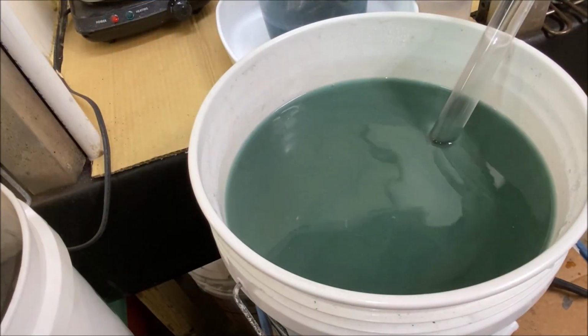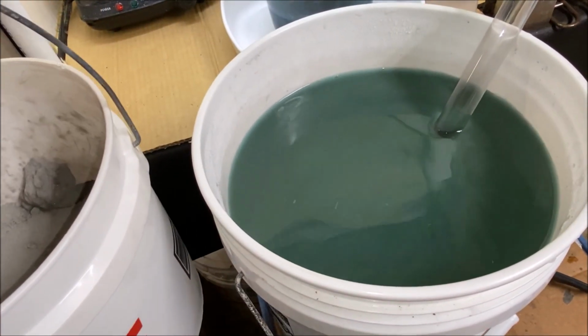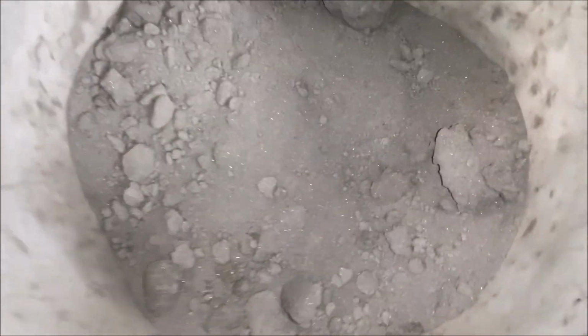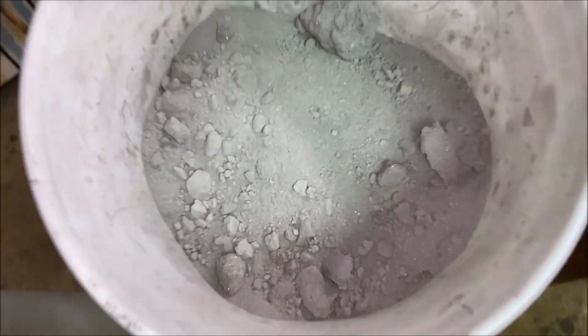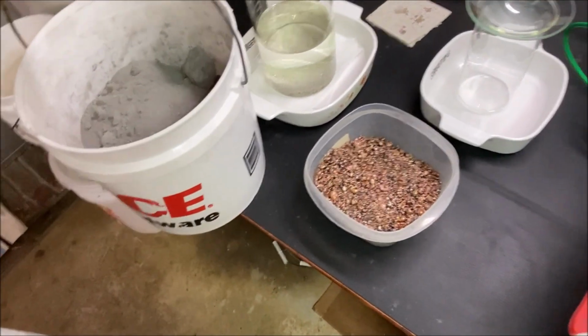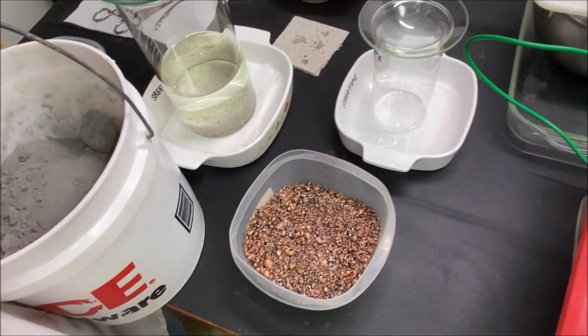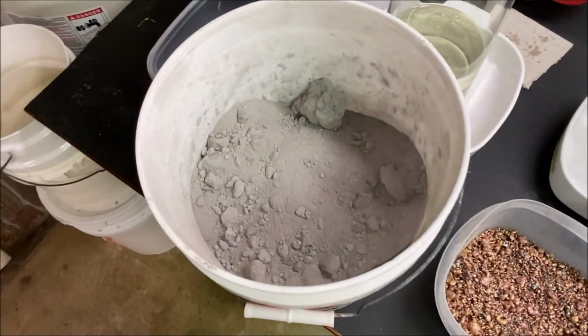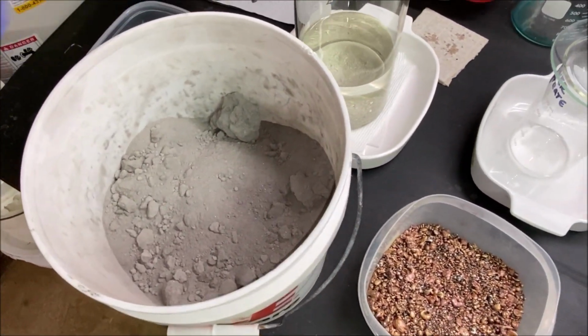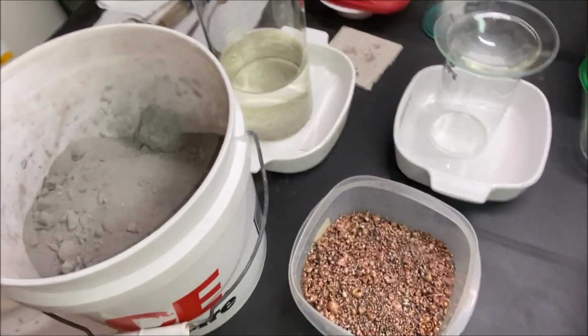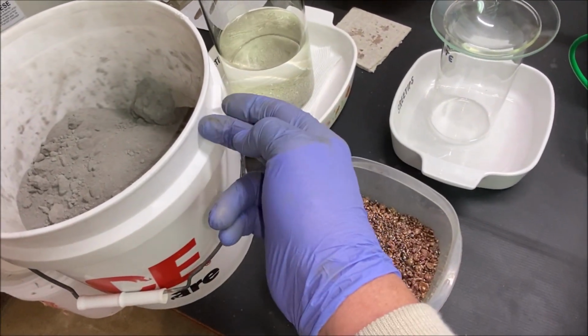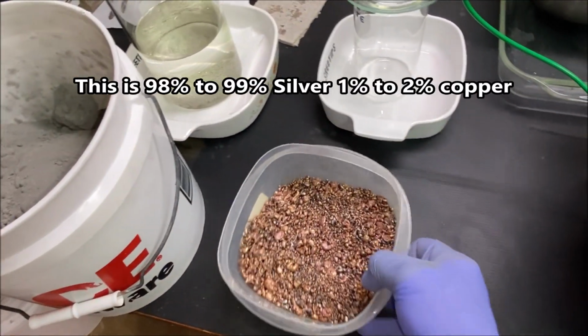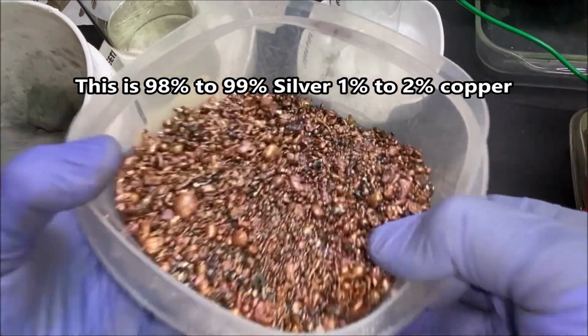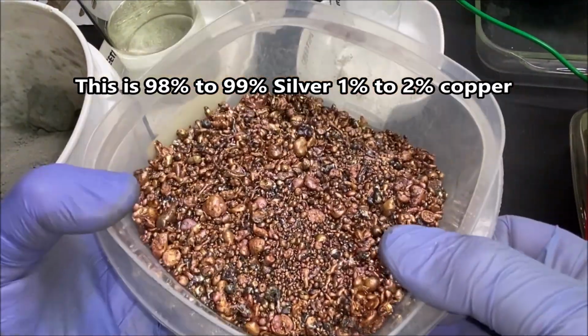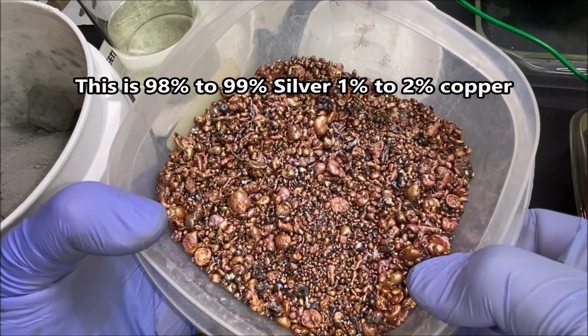When this reaction is complete, I drain all that blue liquid off of there, and I end up with a bucket of cement silver that looks like this. And what I do then, that's about 25 pounds of silver in here. What I do with it is I melt this cement silver into shot. And that's what this is. I melt it, pour it in water, and make these little granules, these shot.